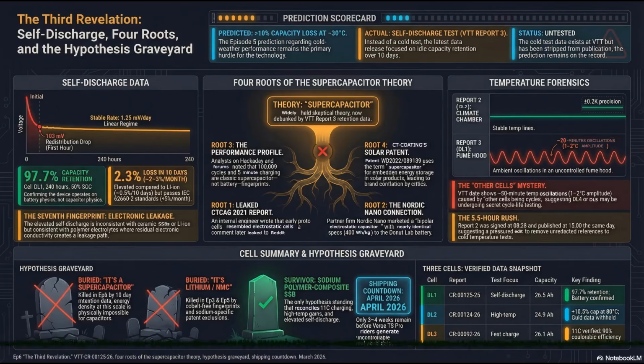So what is the sole survivor? What is the only theoretical architecture still standing that perfectly accommodates all 7 physical fingerprints we've collected? It has to accommodate the 11C charging speed, the bizarre high temperature love, the specific linear voltage curves, the roll-to-roll screen printing manufacturing process, the complete lack of lithium, the requirement for mechanical pressure to maintain contact. And now, the elevated 2 to 3% monthly self-discharge rate.